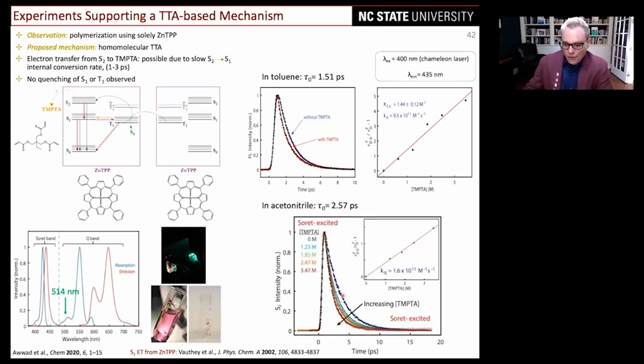The S2 excited state is here, but you can see systematically with increasing concentration of the TMPTA acrylate, we get a linear Stern-Volmer plot. And they look weird because now we're doing ultrafast quenching, so they're way above diffusion limits. That's why it's 10 to the 11th per molar per second. But it verifies the fact that you can absolutely see that we're getting dynamic quenching of the S2 excited state in the porphyrin by the acrylates.